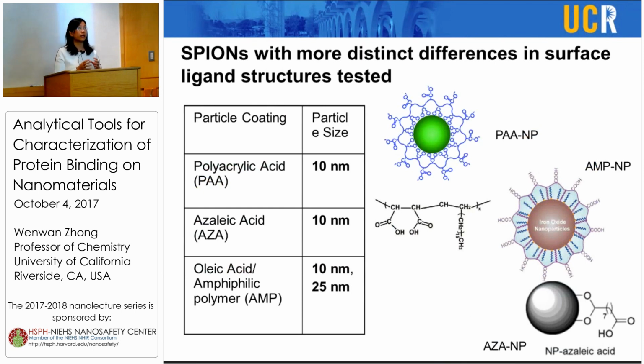But this time the coating could be either polyacrylic acid, which is very hydrophilic with a very dense carboxyl group on the surface, or azelaic acid, where after a certain treatment we actually remove half of the carbon chain. So then it has a smaller number of carboxyl groups on the surface. And then we also bought some iron oxide particles coated with oleic and amphiphilic polymers. So this is kind of the in-between.